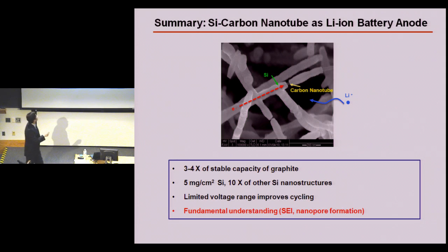So, summary for this part, basically I showed you how we can fabricate this interesting core-shell structure. The nanotube will take care of the electron transport, and also the nanotube will function as a mechanical framework for silicon deposition. And this core-shell structure will effectively decrease the diffusion length for the lithium inside the silicon. And we get a very good mass loading, and also a very good capacity. With limiting the cycling voltage, we get very stable cycling performance as well.